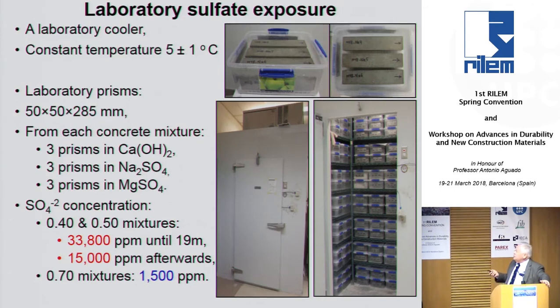And we did some in the laboratory at 5 degrees Celsius, where we stored concrete prisms in containers in various solutions of either mag sulfate, sodium sulfate, or calcium hydroxide as a baseline, and we used different concentrations depending on the water binder ratio.